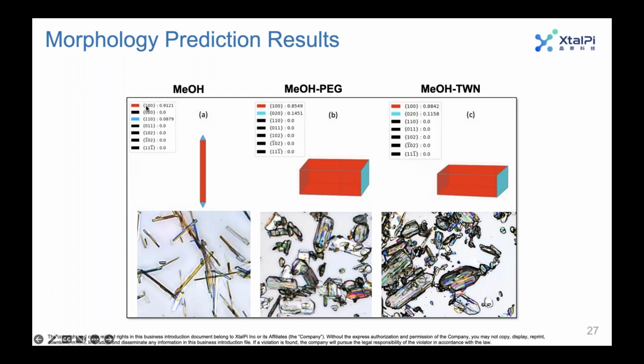You'll notice here that you can see the crystal faces that dominate or make up the morphology. So in pure MEOH, we see that the 100 face is by far the dominant face of the morphology, and we see a small percentage of the surface area taken up by the 110 face. But when we add PEG or tween, we see that the 110 face disappears from the morphology and it's replaced with the 020 face. So we'll talk a little bit about how that happens later on and what the simulations can tell us about that specific change.